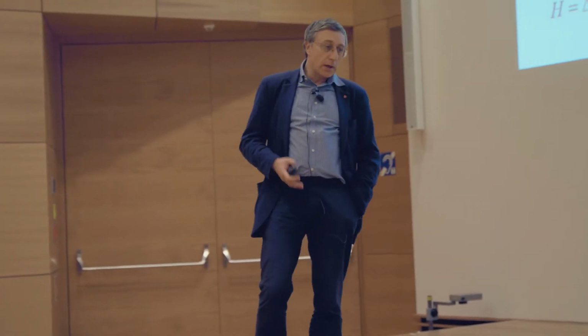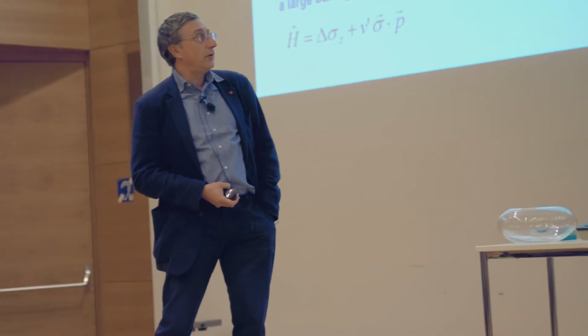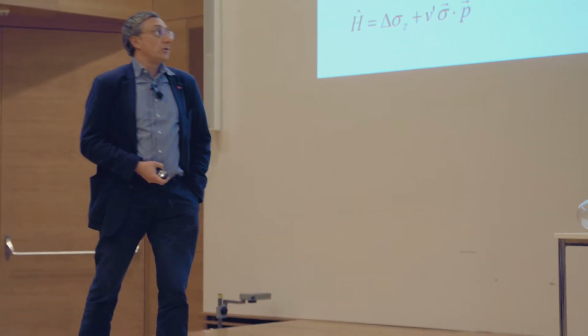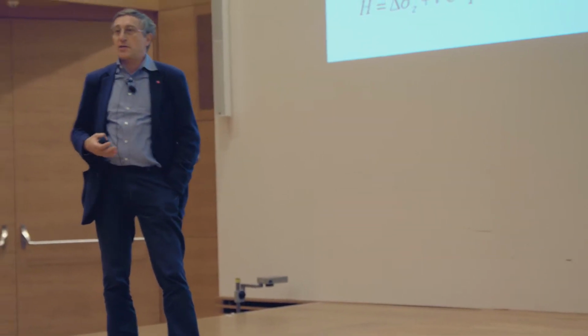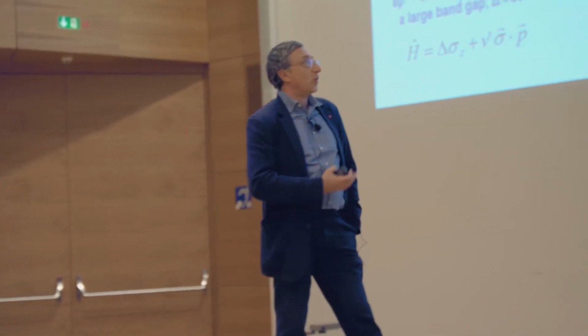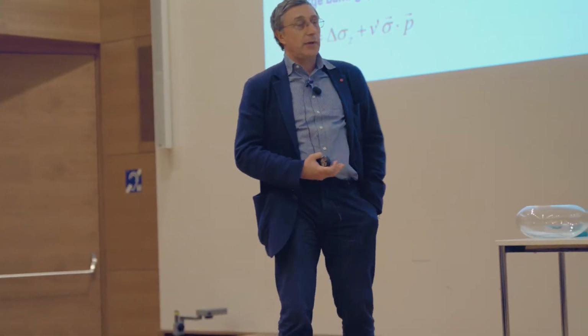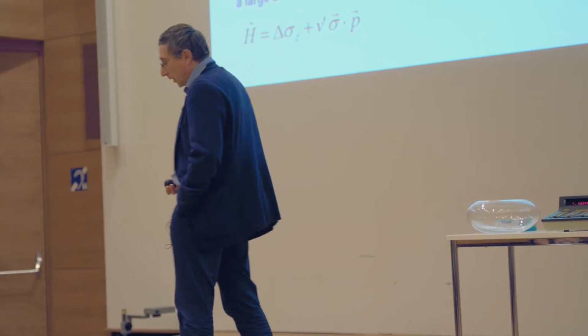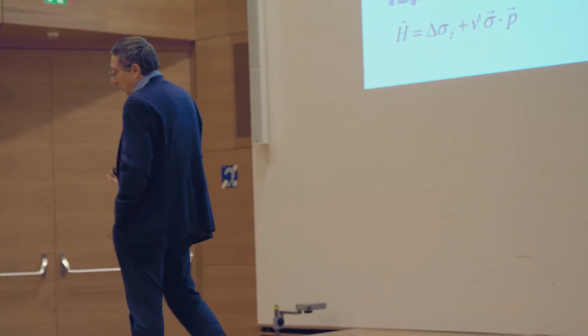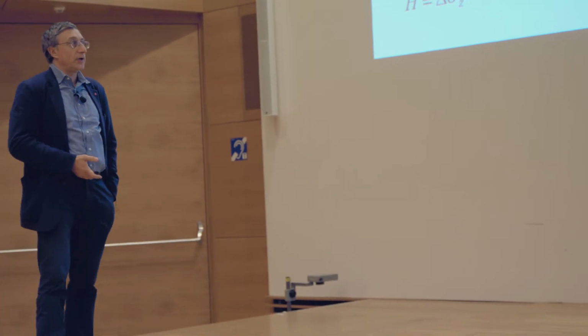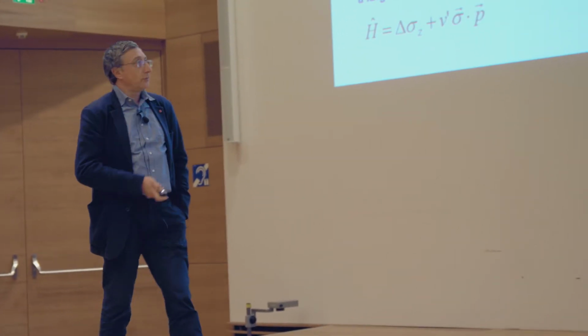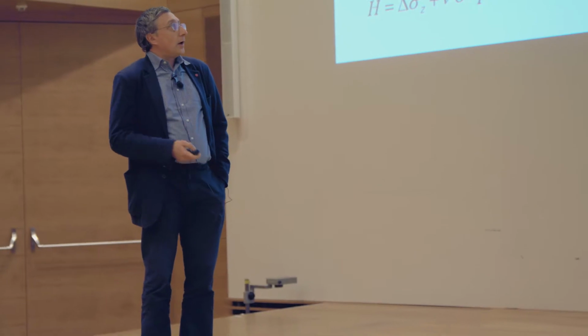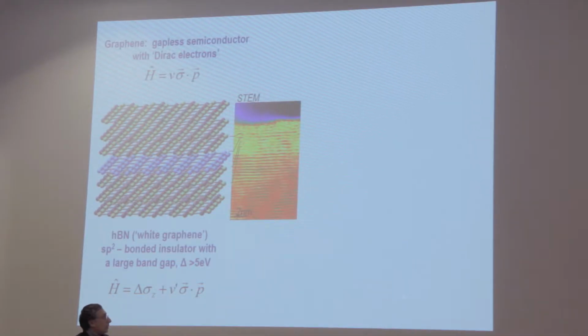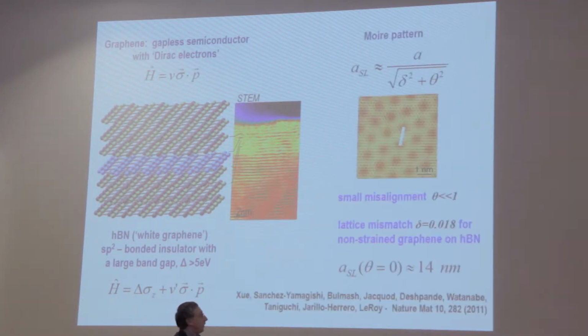of boron nitride. Carrier density can be changed in graphene by a lot, and also one can perform very precise capacitance measurements, detecting small changes in the density of states of electrons in the system you want to study. And if you start seeing large variations, this would be indications for gap formation. Graphene is a system where the electrons are characterized by the Dirac equation close to the neutrality point of graphene.